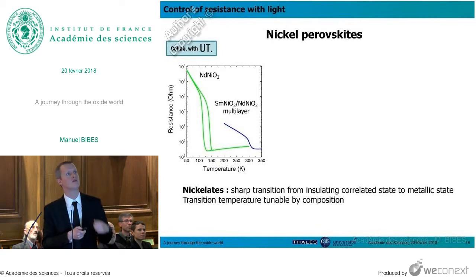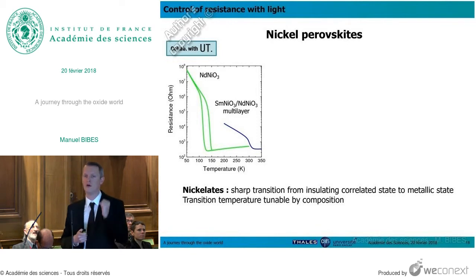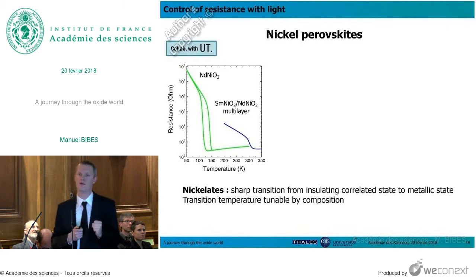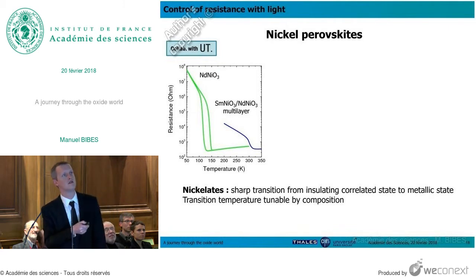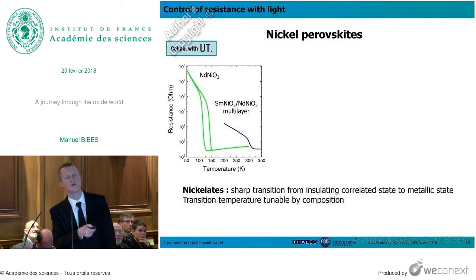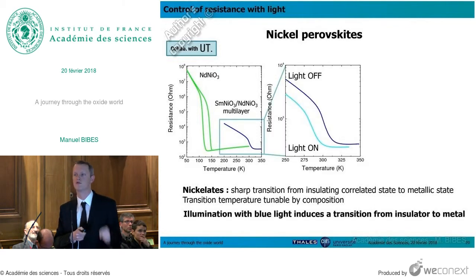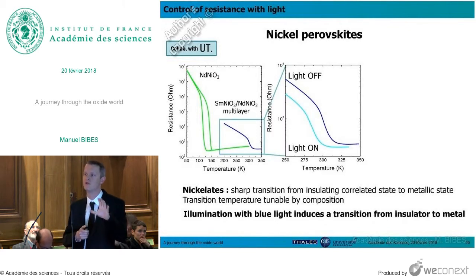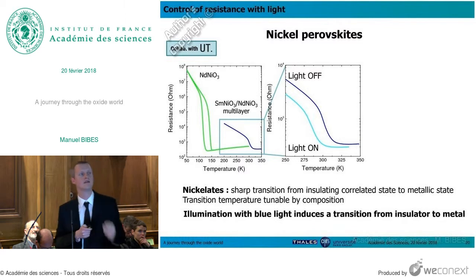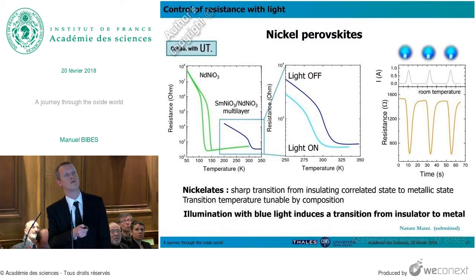And now we are going to use light to manipulate the resistance state. And so this is a curve taken with the light off, and this is with the light on. And you see that we have a very strong decrease of the resistance at room temperature. So we have some kind of switch of resistance which we activate by the light. And this is maybe easier to see here. When we apply a pulse of light, the resistance decreases by a factor of 2 or 3.